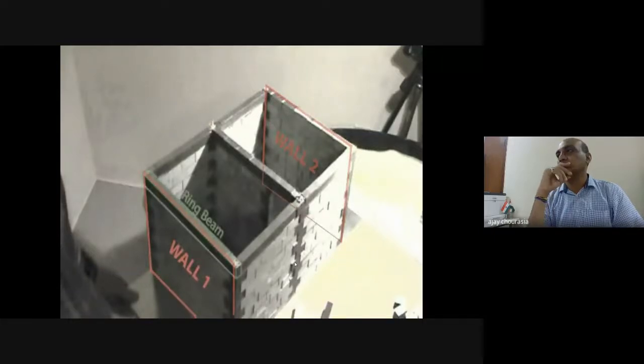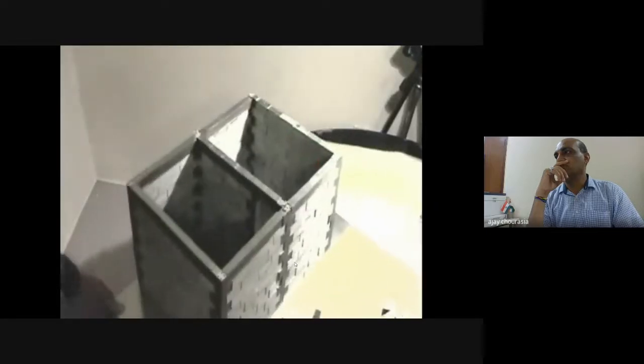This front wall has a ring beam on top of it, which will help to restrain this wall out of plane along the top edge. The rear wall here does not have this ring beam, so we can make a pretty good guess as to which one will fail first. Just as we might have expected, the wall without the ring beam supporting its top edge failed first, and we can thus conclude that the ring beam plays a crucial role in the out-of-plane stability of a confined masonry wall.